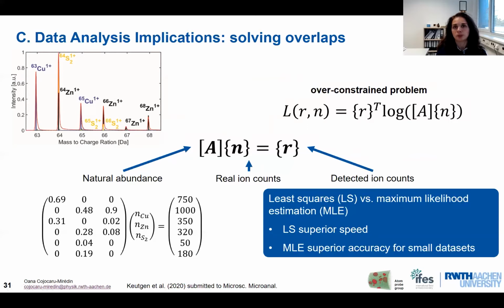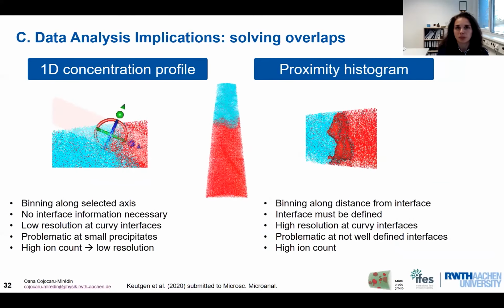So if you want to resolve peak overlap in a very small defined volume, this will not be that accurate. By applying the maximum likelihood method, we are able to accurately resolve peak overlap in very small volumes. And this method has been applied for resolving peak overlap at the interface region. And we have shown and explained this nicely in our paper submitted recently to the Microscopy and Microanalysis journal.